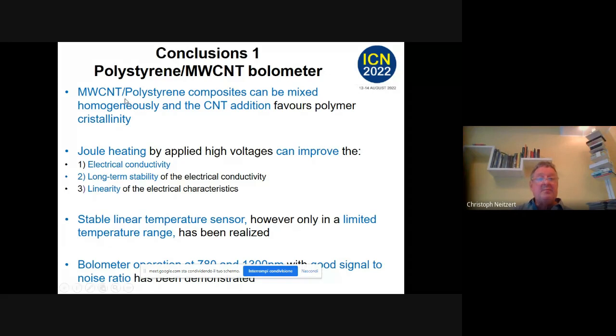Okay, what we can see: multiwall carbon nanotube polystyrene composite can be mixed homogeneously, and this addition favors polymer crystallinity. Joule heating by applied high voltage can improve the electrical conductivity, the long-term stability, and the linearity of the electrical characteristics. We had a stable linear temperature sensor, only in a limited temperature range, about 50, 60 degrees. But bolometer operation at 780 and 1300 nanometer had been shown with a very good signal-to-noise ratio, that even if the temperature coefficient is very low, that is due to the excellent stability of the electrical characterization.